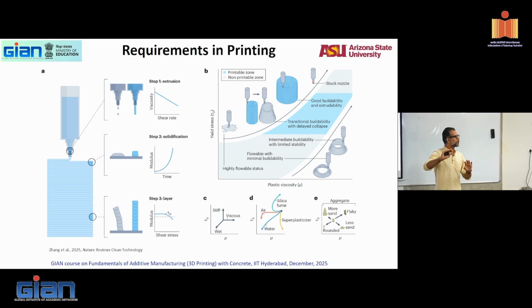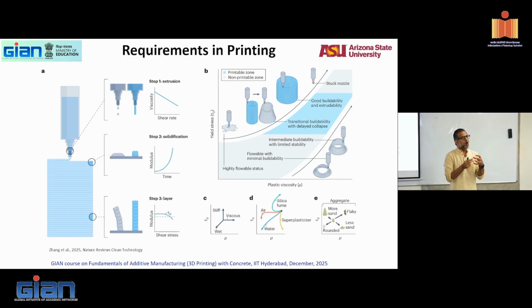But then that's a slow process. So what I want is to set the system up in a way that can get a quick modulus. How can it be? So I have one particle here, one particle here. The combined modulus should increase faster. The glue should happen faster. Which means I need to make sure that the particles are packed well enough so that the cement paste around it quickly hydrates and creates a network so that the combined modulus of the system goes up higher. Is it clear? You see the importance of particle packing? The particles have to be packed well. So that is what you want to get the modulus higher.